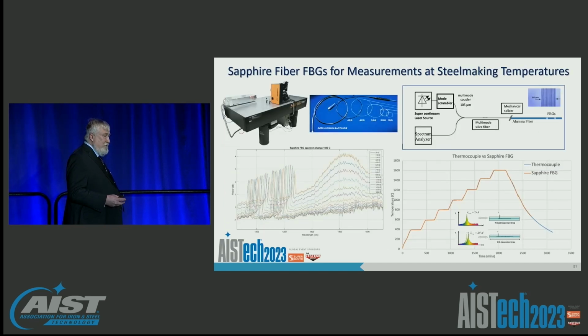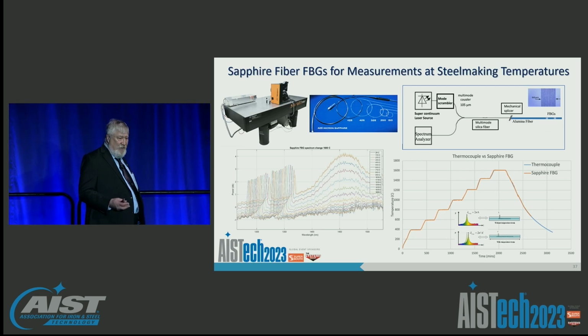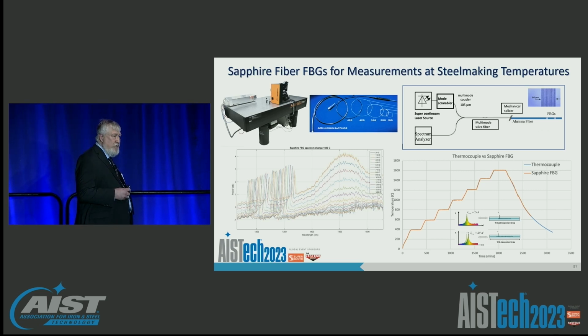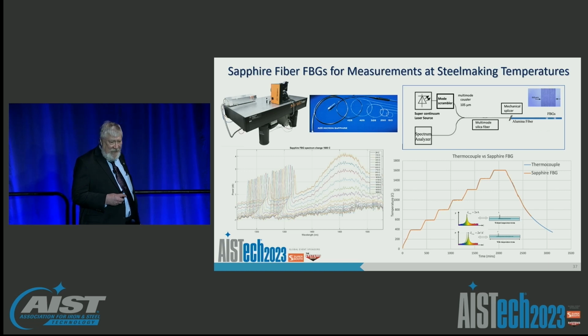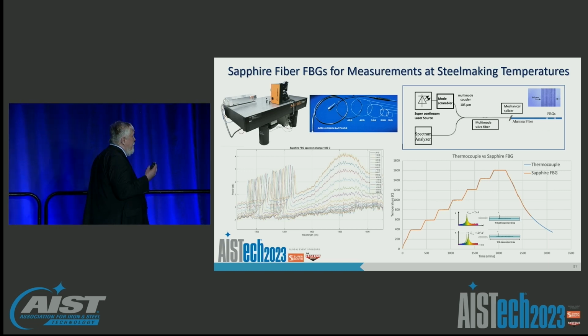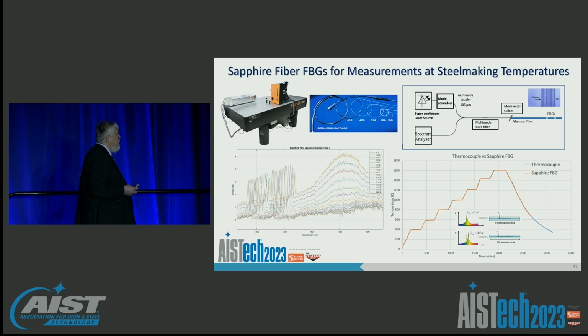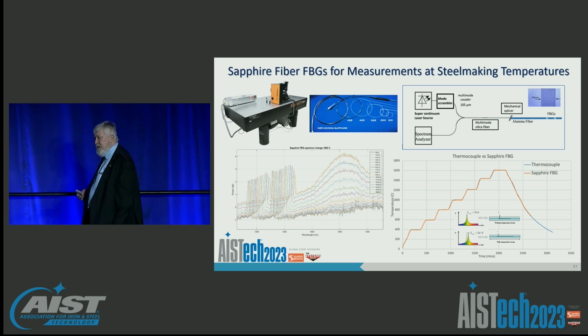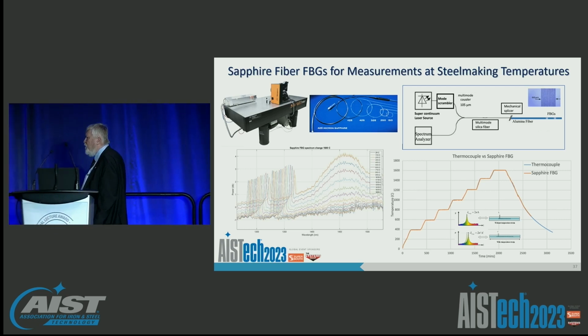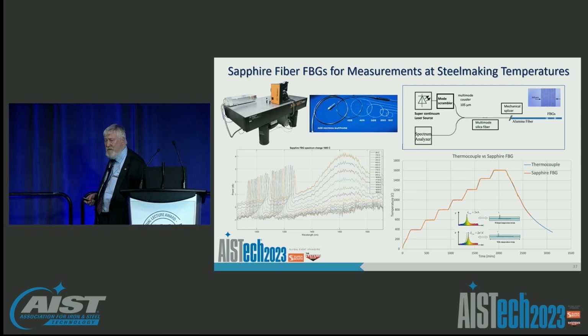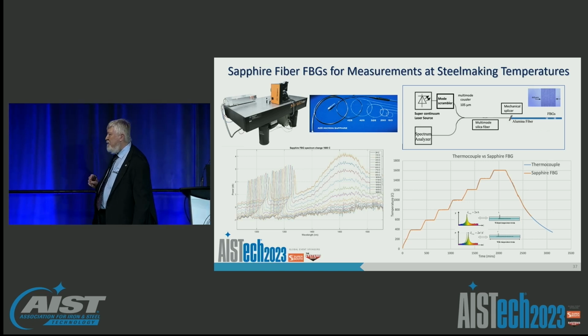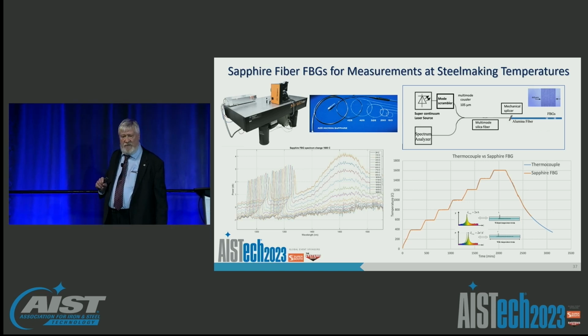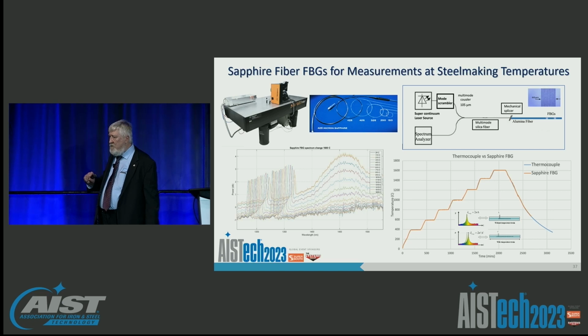So I mentioned that we did some measurements in aluminum, but if you're like me, you want to do it in steel, right? So how do we do that? One way we do that is we move to a different fiber. In this case, single crystal sapphire fiber, which can be grown now to, as I said, about 2 meters in length, about 125 microns in diameter. And that diameter is too wide for it to serve as a single mode fiber. So it's a multi-mode reflector, and so we have to do special things.